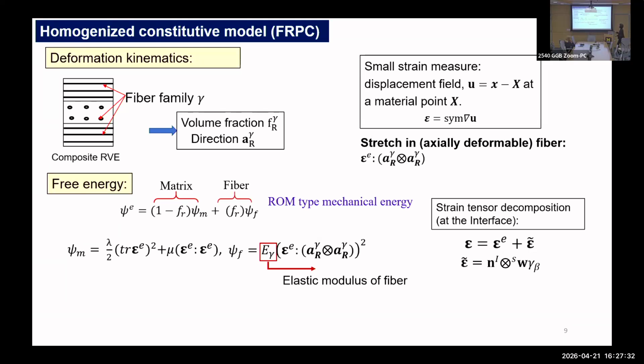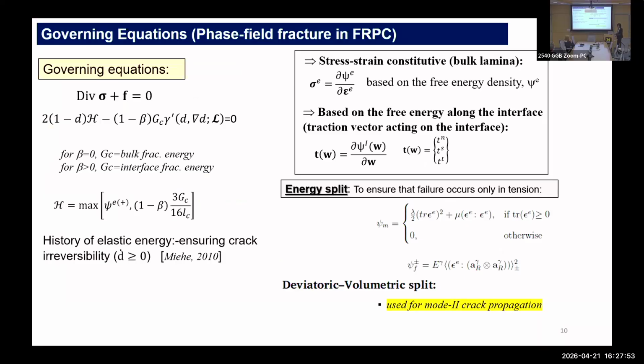So we can basically fit the material parameters to match the elasticity. So this is what we started. So yes, according to your question, there was anisotropy because we just took axial stretch in the fiber orientation direction for the fiber part of the free energy. So with this very simple constitutive description, we went ahead and applied the variational principle to get the governing equations. So we have the classical stress equilibrium and of course the phase field equations.